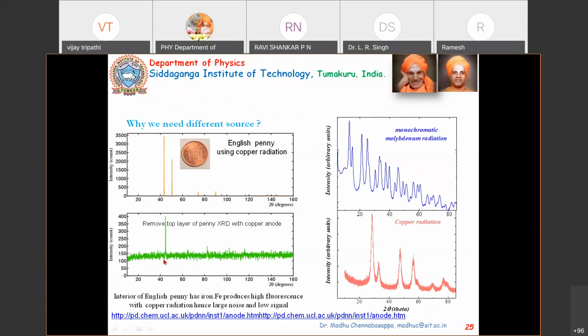So in this case, even if you take the scan for the same time, same settings, you can see here for copper 3500 was the highest intensity, but in the case of iron, with the same setting, the highest intensity is 400, which is almost 10 times less than the previous one. So this is mainly because of the copper radiation. Instead of this copper radiation, if I use a cobalt radiation, this intensity would increase. So I would get a good intensity, less noise.